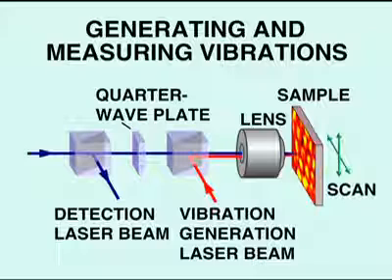To produce vibrations, what we effectively do is take a hammer and strike the plasmonic crystal. These vibrations show that it's not just a plasmonic crystal, it's also a phononic crystal. Actually, instead of a hammer, we use ultra-short light pulses. In the experiment, red laser light pulses create tiny vibrations by heating a small submicron spot. Blue light pulses detect the vibrations through intensity changes at the same point.